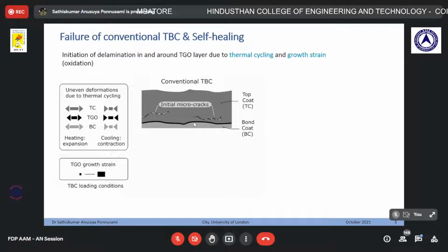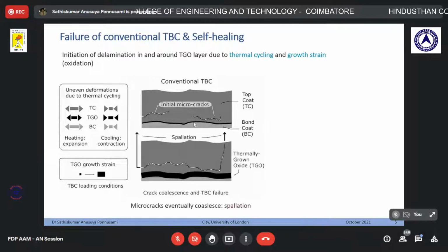Okay, but if it keeps growing, what happens? You are adding additional heterogeneity into the structure, which means the stresses would be more and more, which means the micro cracks would become more and more. But in the end, if you leave the micro cracks to form and grow, ultimately all these micro cracks coalesce, and then they form a major crack, which leads to the entire failure of the blade, not the blade, but the coating. Yeah, and which we call spallation.